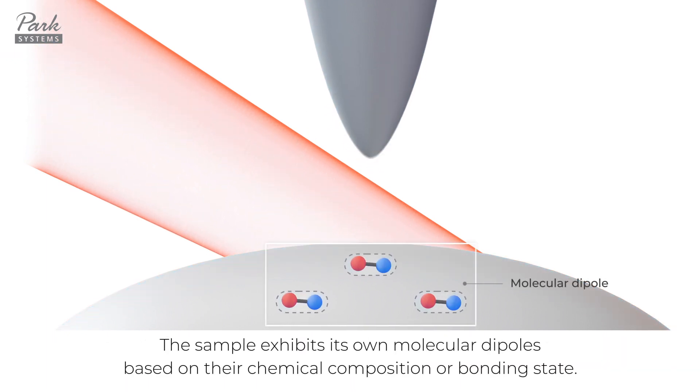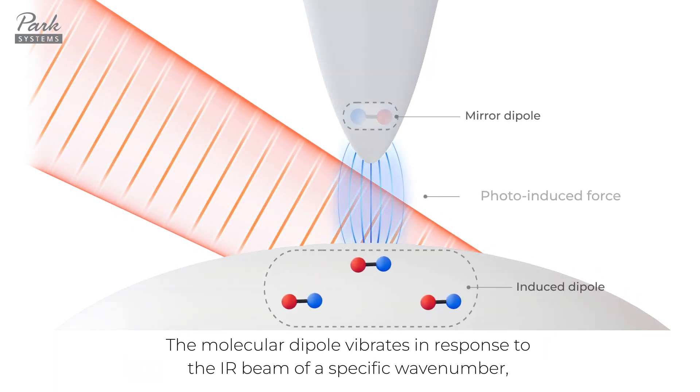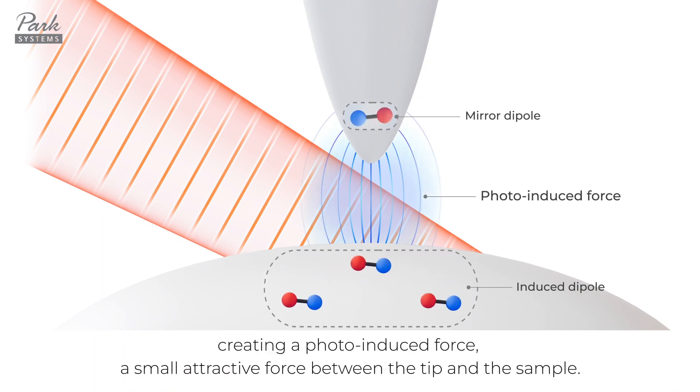The sample exhibits its own molecular dipoles based on their chemical composition or bonding state. The molecular dipole vibrates in response to the IR beam of a specific wavenumber, creating a photo-induced force, a small attractive force between the tip and the sample.